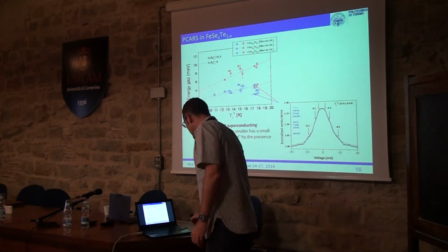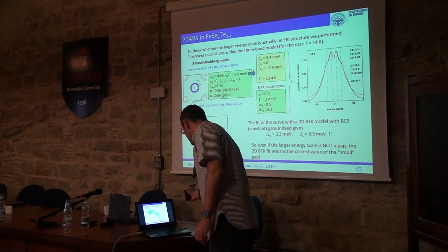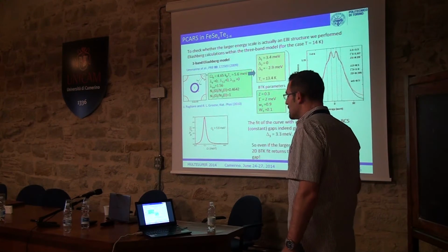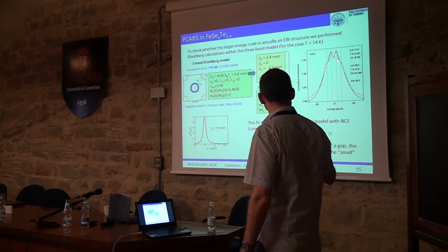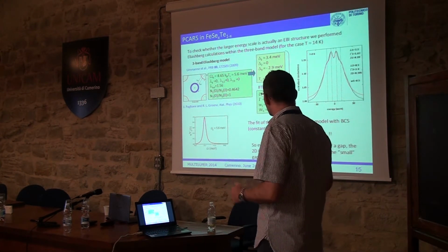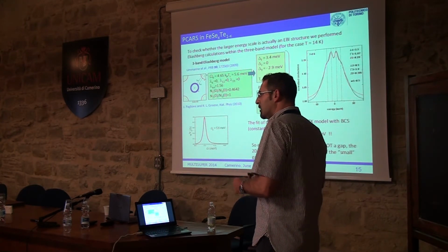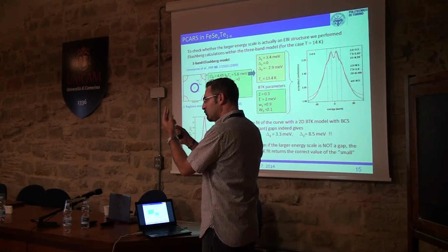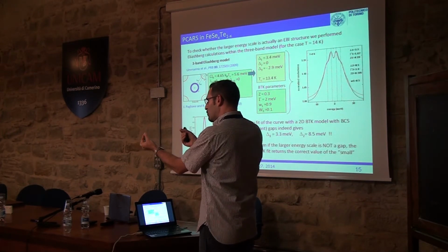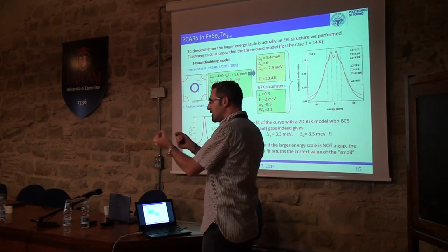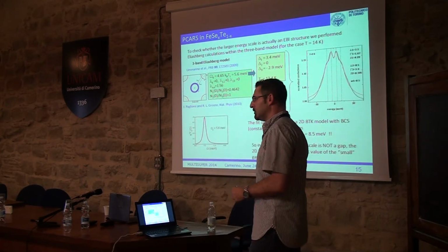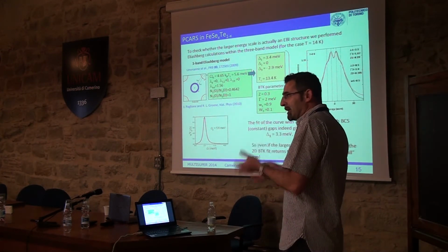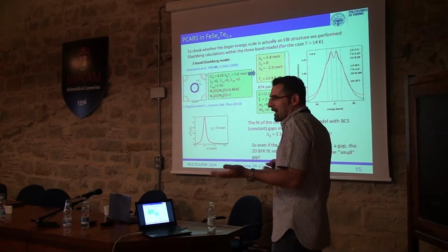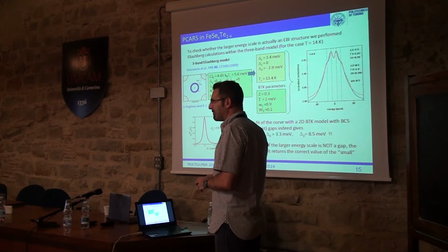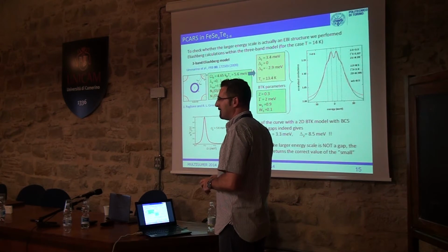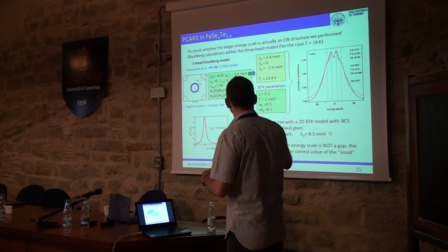Ah, you mean in the theory? Well, yes. We have made different calculations. You can make these shoulders more or less evident by changing essentially the lambda, because you have two different lambdas, which are free parameters. By tuning lambda 1,3 or lambda 1,2 in a different way, you can make them more or less visible. But it's a fact that also in reality they can be more or less visible. That I don't know why. So in the experiment there is a clear difference between films and bulk. Yes. In the theory you just choose the parameters.